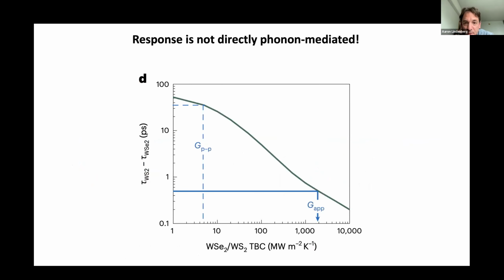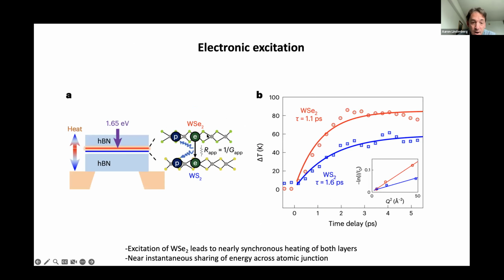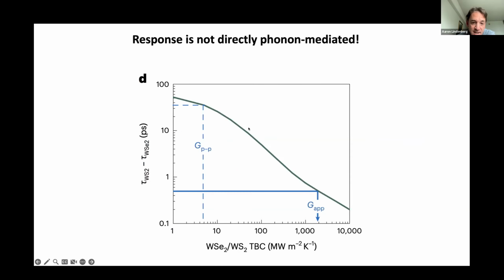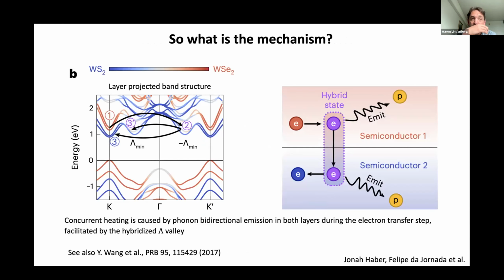So the first thing you can say is that this response is not directly phonon mediated. It's not essentially associated with thermal transport, right? Of course, in the first step, we create a very hot top layer. And so you could ask, well, maybe energy is just directly shared using the thermal boundary conductance that we just measured. But what you can show is that using the TBC that we extracted in the first part of these measurements, this would have given rise to a very large time delay in the heating of the underlying layer, many tens of picoseconds. So you would need an abnormally large thermal boundary conductance to enable energy sharing through this perspective. So it's got to be a more complex electronic, charge transfer mediated process.